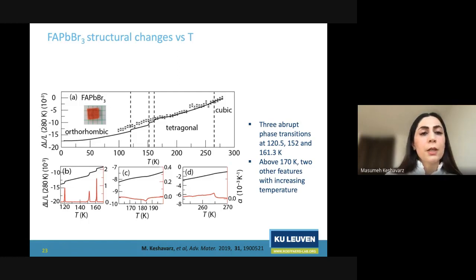Then going from iodide to bromide, again, the phase diagram is much more complex compared to the iodide one, and we see the cubic phase at room temperature. Then by cooling down the system, we reach the tetragonal phase. We identified these structural phases through XRD measurements, and the accurate temperature at which the transition happens through dilatometry, or thermal expansion measurements. We couldn't identify the structures in the regions where we have structural changes in the thermal expansion through XRD because it's not that sensitive, and we think these are some distortions of the octahedra or the orientation of the formamidinium group, which changes the structure. And then by cooling further down, we reach the orthorhombic phase.